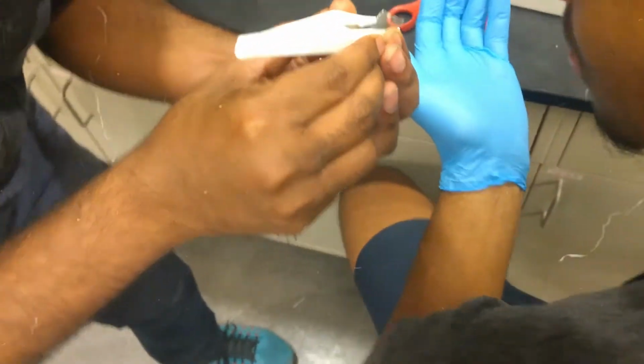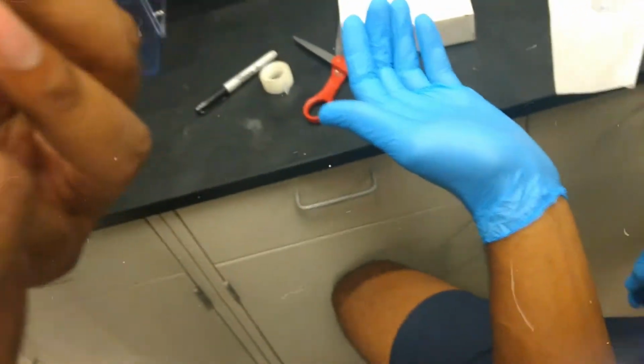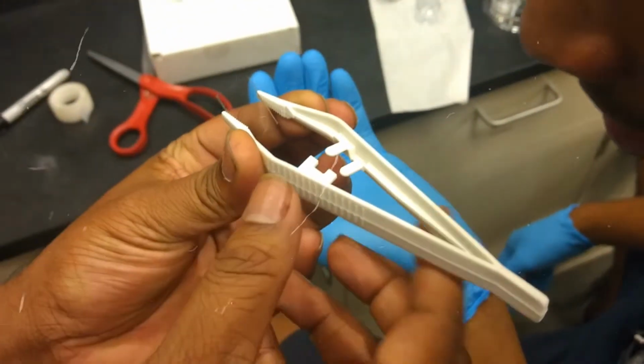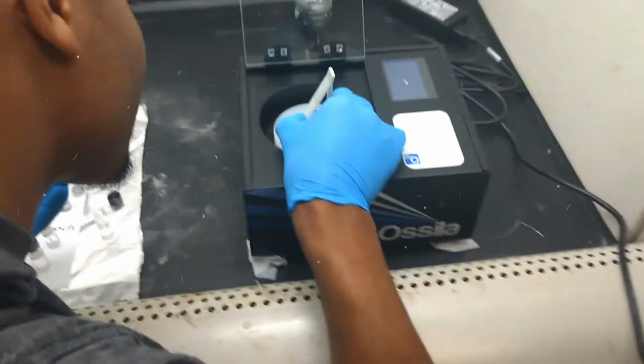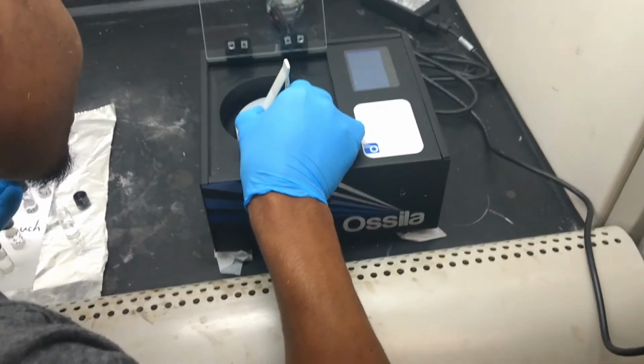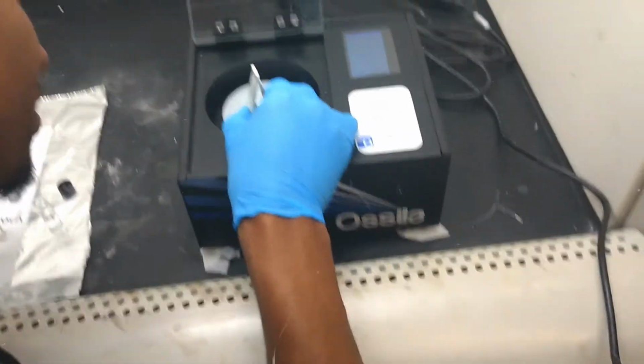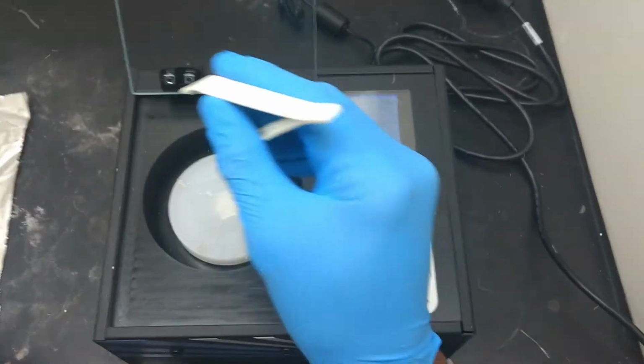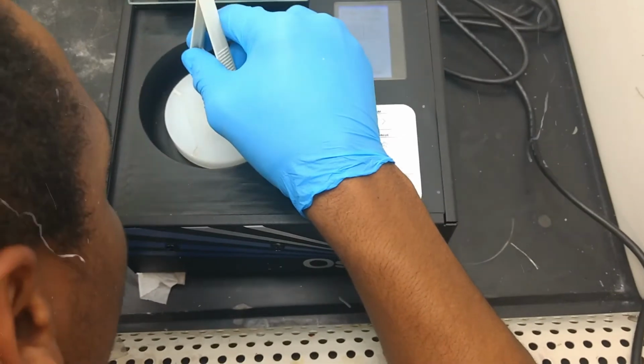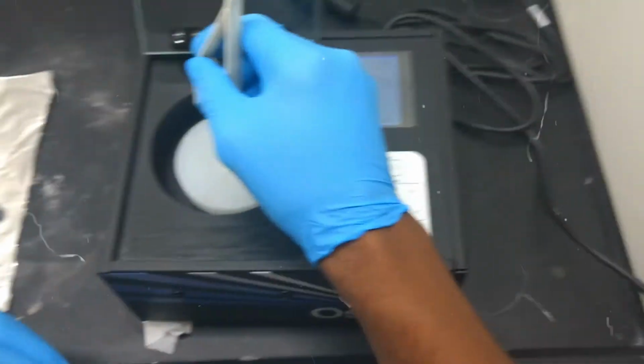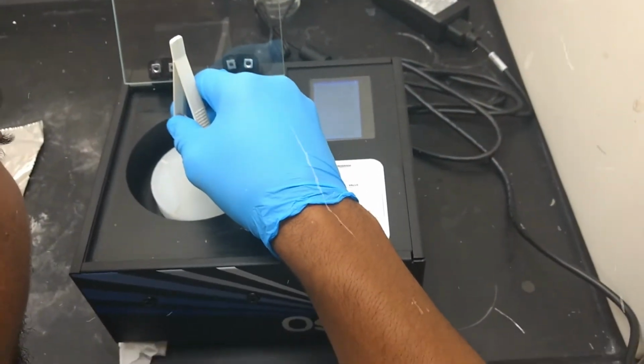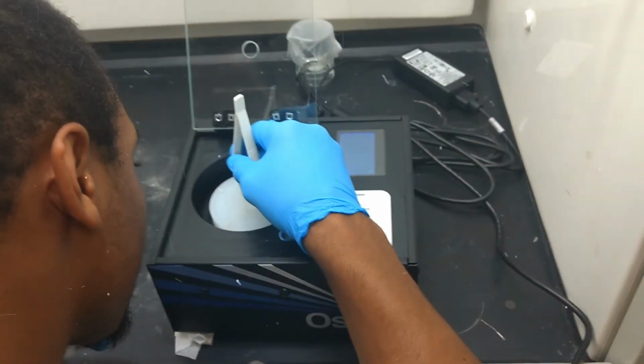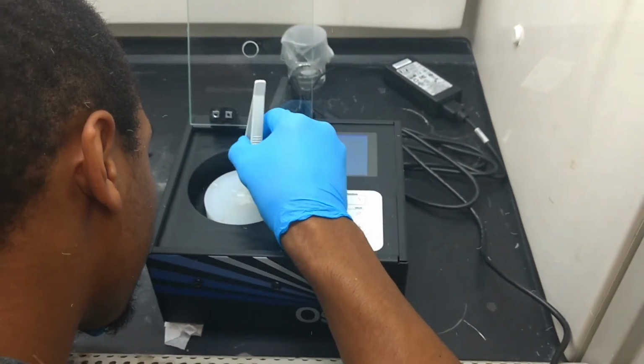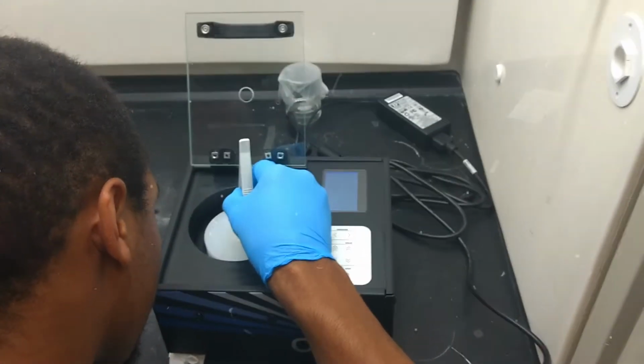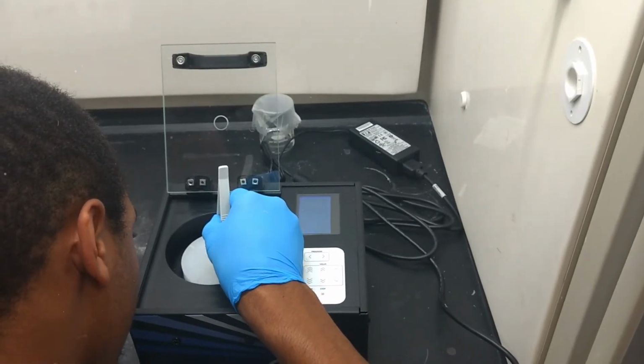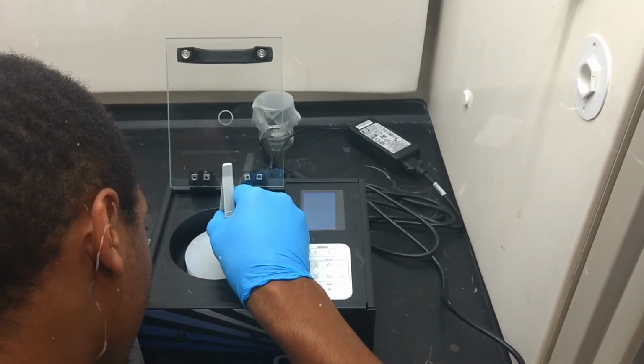The spin coater is programmed to run in 4 stages per iteration. These are the start-up, deposition, spin, and the spin down stages. The start-up stage gets the sample up to the desired spin rate. The deposition stage is when the solution is deposited onto the sample. The spin stage is when the sample is coated, and the spin down stage is the sample slowing to a stop.